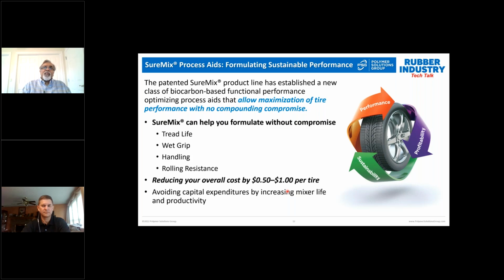We also, by optimizing the mixing process, and we'll share some data with you where we've taken 2 or more mixing passes out of a mixing cycle, can help reduce the cost. It's not just the cost of mixing; it could be substituting materials, or improved extrusion rates, which helps reduce cost. We helped a natural gas hose manufacturer reduce mill time from, I would say, 20 minutes down to 2 minutes. They had a tilt mixer which dropped on the mill. So there are many ways where processability improvements impact the cost. And as Aaron emphasized a little earlier, this helps. We also have a biocarbon base which helps our customers achieve their sustainability goals. So let's move on and really see how SureMix works in rubber.